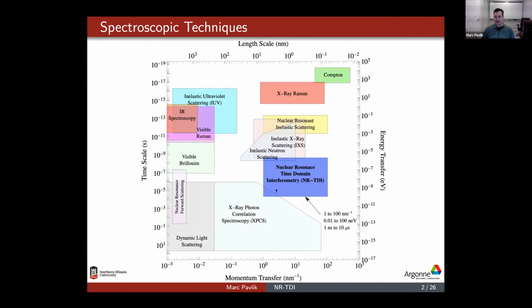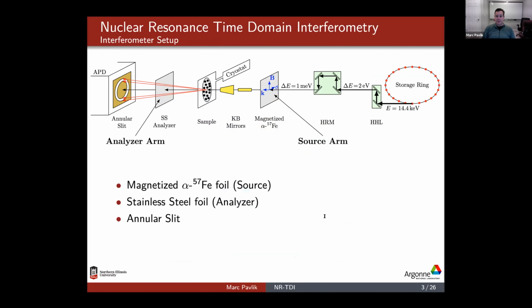What's unique about this technique is we filled this little void where we can make measurements from about 1 nanosecond to about 10 microseconds and a momentum transfer between 1 and 100 inverse nanometers. So the interferometer is set up using a magnetized alpha iron foil as a source arm and using a stainless steel analyzer foil. And then we create an annular slit that allows us to collect the entire diffraction ring.